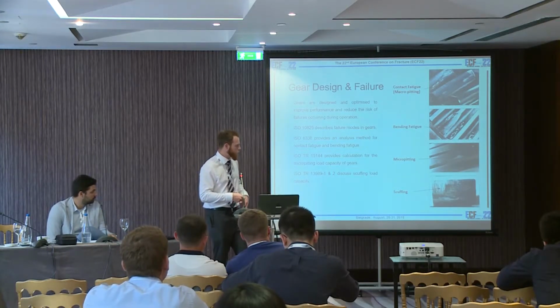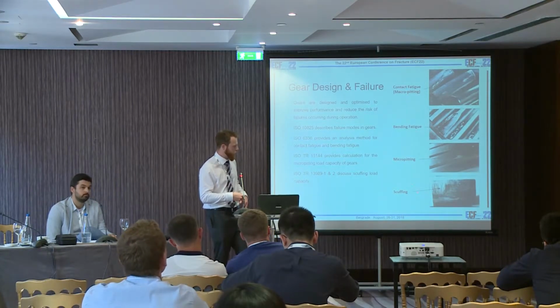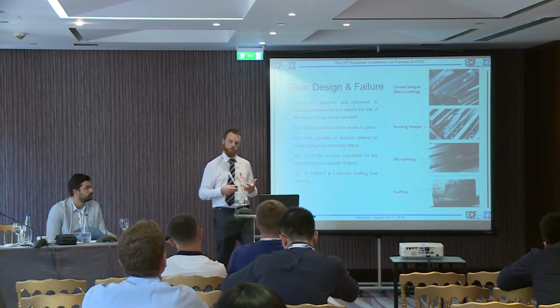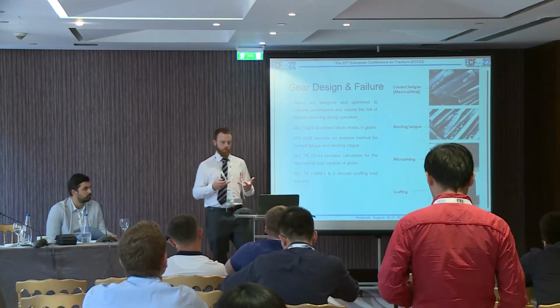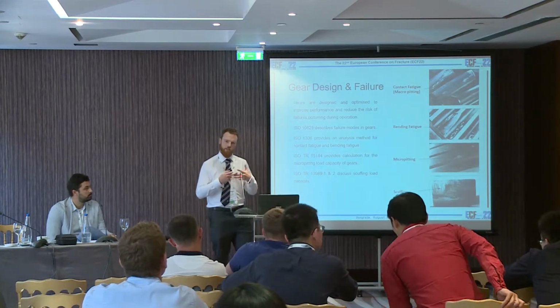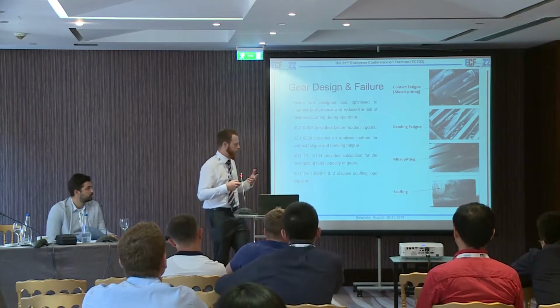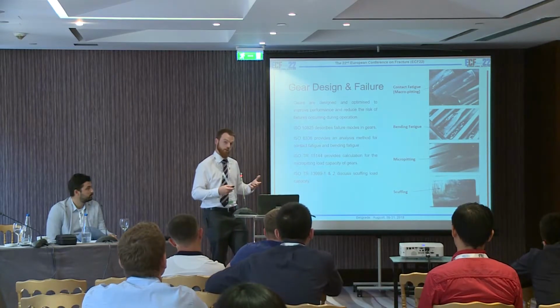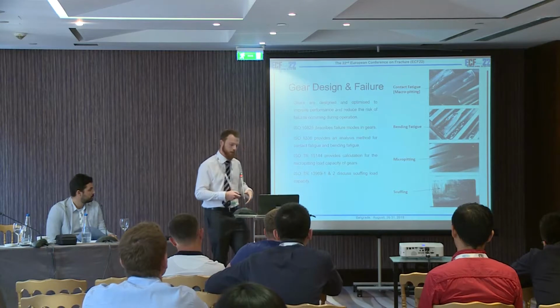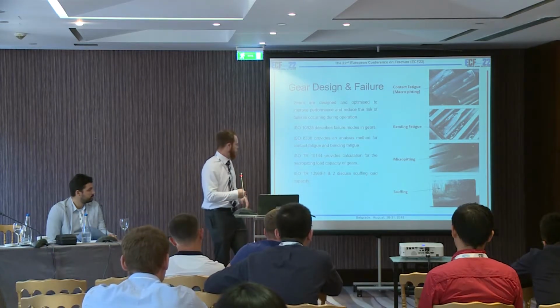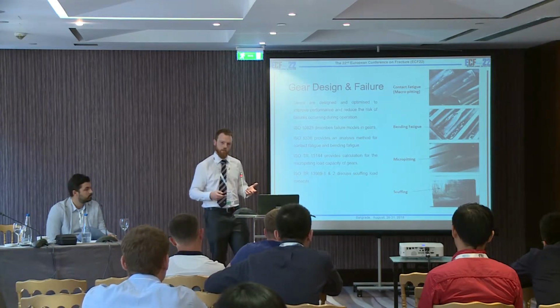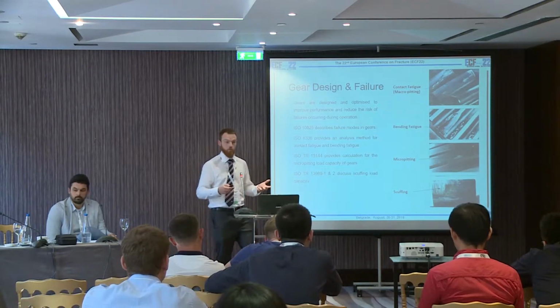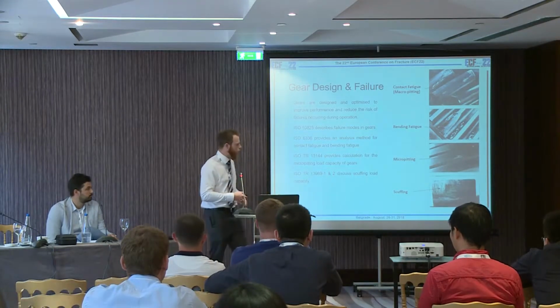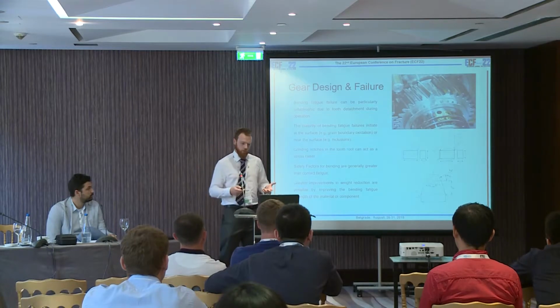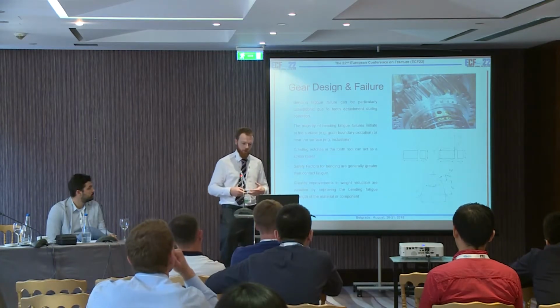And then we have more instantaneous failure modes, such as scuffing. This is just one example. Scuffing occurs when we have instantaneous breakdown of the lubrication film thicknesses. We end up with metal-metal contact of the 2 gear teeth, and because of the high sliding speeds, there's instantaneous welding and tearing. So yeah, these are instantaneous failure modes. And there are standards, I've listed some here, that describe how gear designers can look at how likely that is to happen in operation. So to talk a little bit more about bending fatigue, since that's what we were testing for.